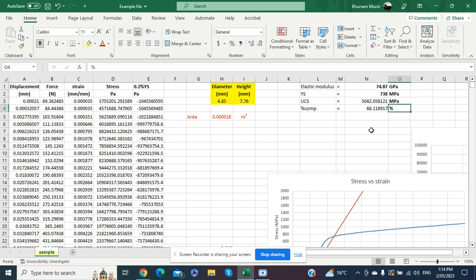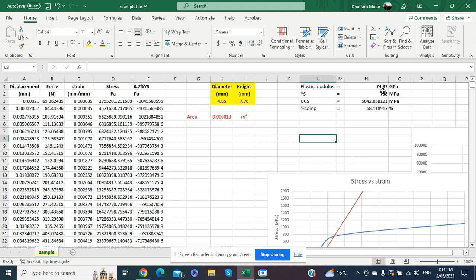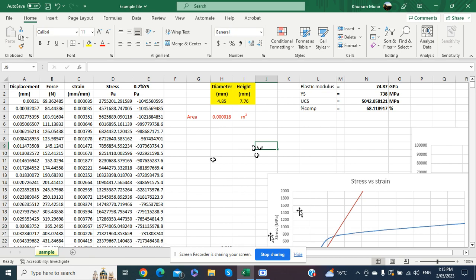In this way we have calculated all four mechanical properties — elastic modulus, yield strength, ultimate compressive strength, and percentage compression — from a given set of compression test data. You can follow this same example for your own data. Note that if you balance the force and displacement before starting the compression test, you will not need to apply the 0.2% offset correction to the yield strength line. If you do not balance them, that error appears in the stress versus strain diagram, but it can be corrected as shown. Thank you very much.